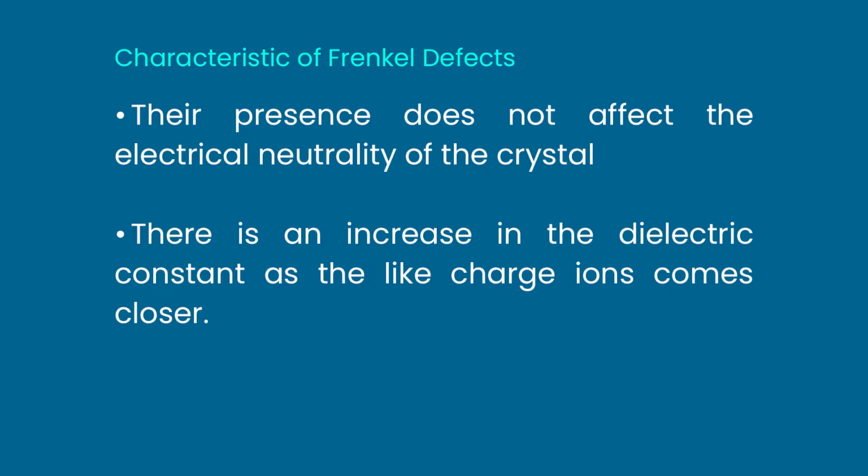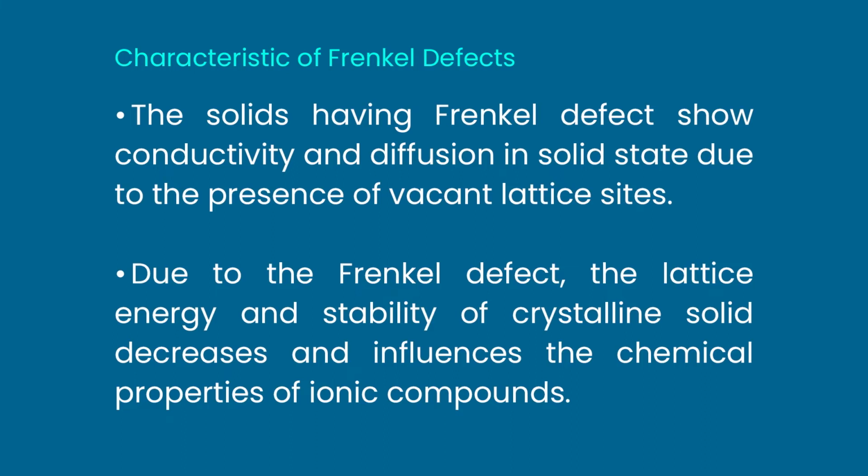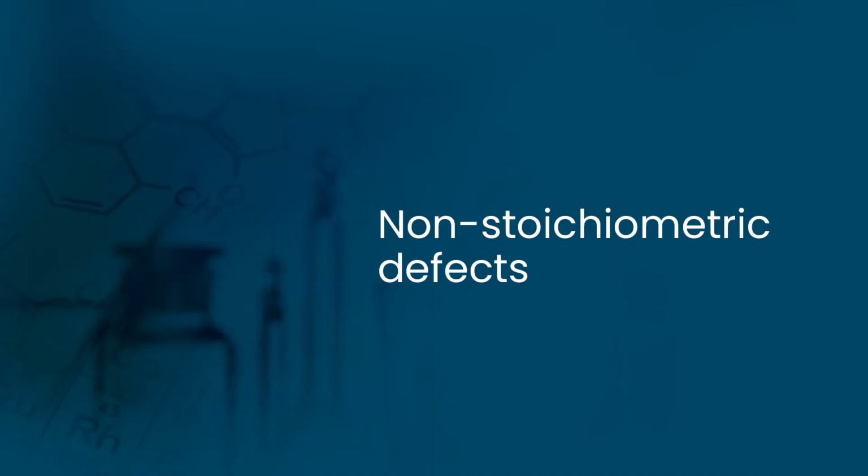Their presence does not affect the electrical neutrality of the crystal. There is an increase in the dielectric constant as the like charge ions come closer. The solids having Frenkel defect show conductivity and diffusion in solid state due to the presence of vacant lattice sites. Due to Frenkel defect, the lattice energy and stability of the crystalline solid decrease and influence the chemical properties of ionic compounds.